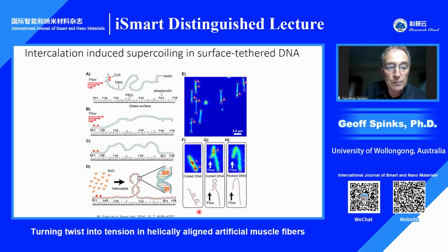Here's another example. This comes from Cees Dekker's lab in Delft. Here, a double-stranded DNA is tethered to a functionalized glass surface, tethered at 2 points. It's then acted on by another type of intercalating small molecule, this time Sytox Orange, and that produces supercoils, and they can be directly imaged as shown there on the right. So DNA, which you might think of as a twisted fiber, if it can be swollen by some sort of swelling agent, small molecule, it produces supercoils.